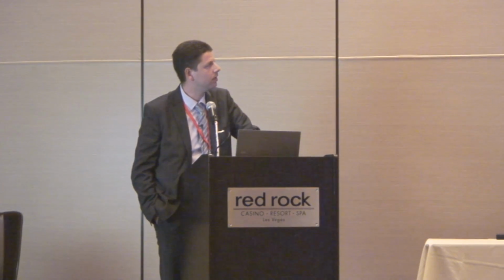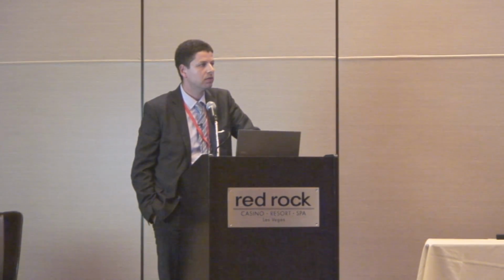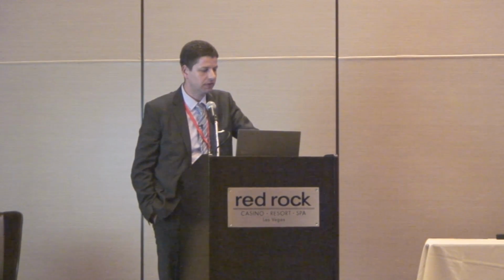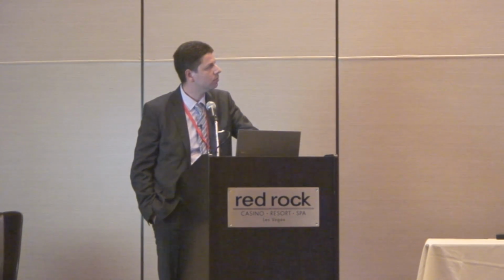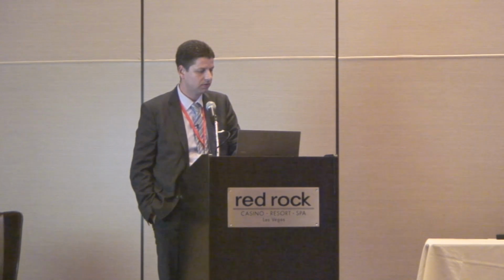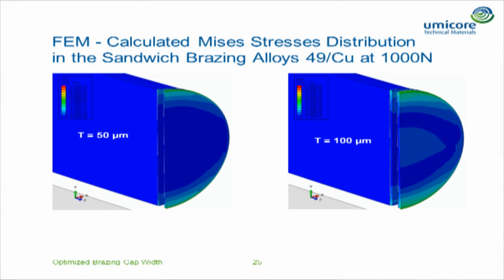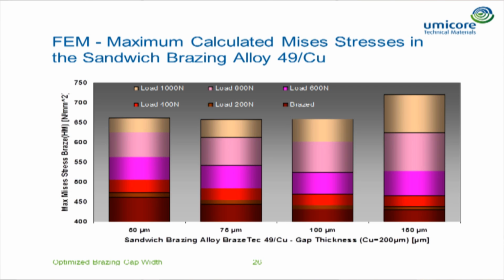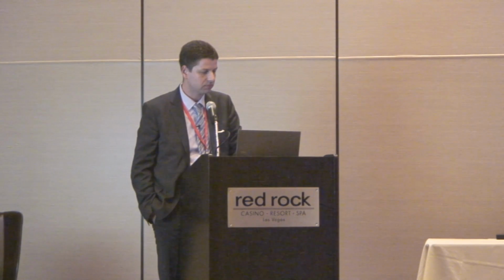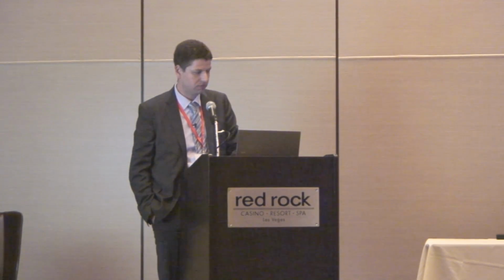When we look also into the brazing alloy layer of the sandwich brazing alloys, we can see only slight differences. And we look now also here at the Mises stresses in total. We can see the same tendency for the brazing alloy layer after brazing, but when we put on the load, there's no big difference from 50 microns to 100 microns, only then an increase when we reach the 150 microns.